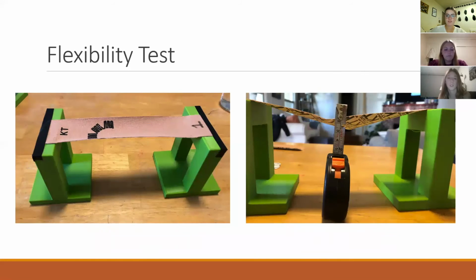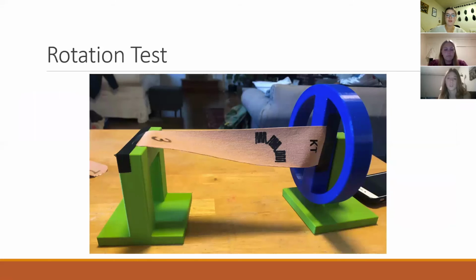Additional tests were performed to ensure the sensors changed in resistance for flexion and extension at various angles. The flexibility test showed that there was no permanent damage after bending the sensors to 90 degrees. Rotation changes were measured by twisting the tape at various angles and measuring the resistance changes. The rotation test showed us that the sensors are sensitive to rotation and able to measure a change in resistance at a low degree of rotation.